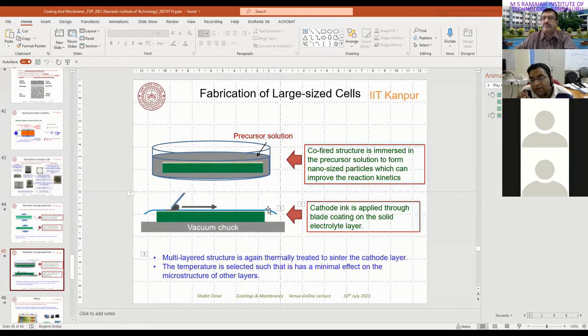So we are coating the cathode over the electrolyte because the cathode can sinter at lower temperature, but you require a higher temperature for your nickel anode to sinter. So it also depends upon what type of combination of cathode, electrolyte and anode that you are using.